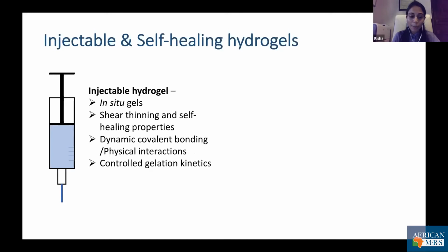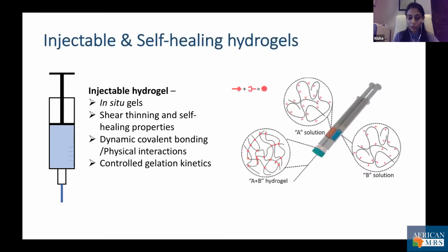Hydrogels require controlled gelation kinetics, that is, they should gel within a given time frame. Another system which proves to be effective for different cross-linking mechanisms is a double barrel syringe, which contains solution A and solution B separately. And when mixed together, they form the gel. You can use a mixing tip so that it instantly mixes the gels into the wound, and in the wound it gels instantly. So the gelling kinetics is also crucial in such a system.